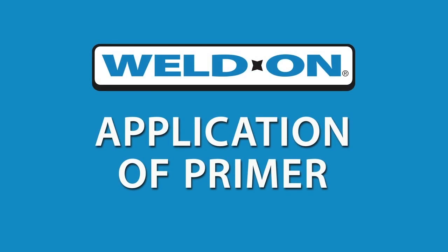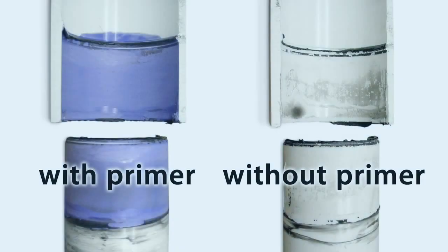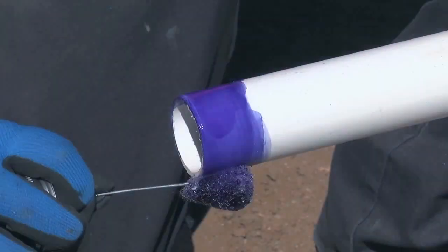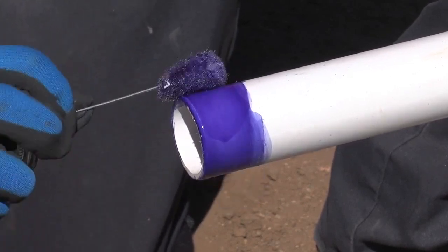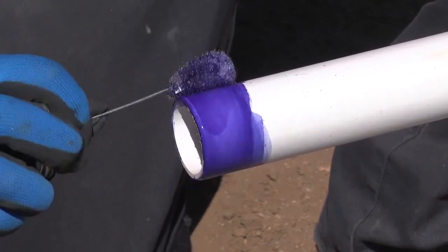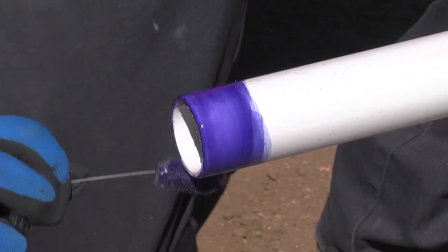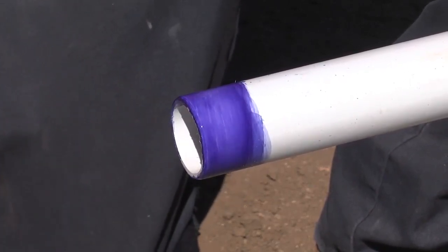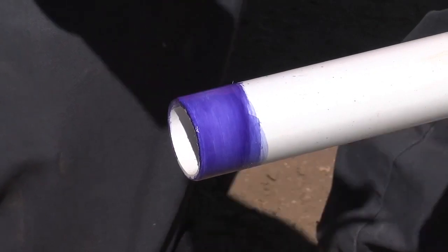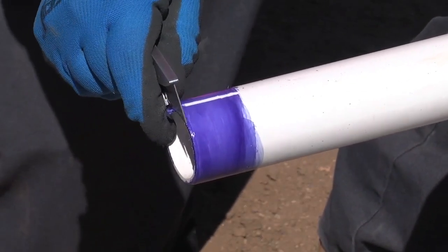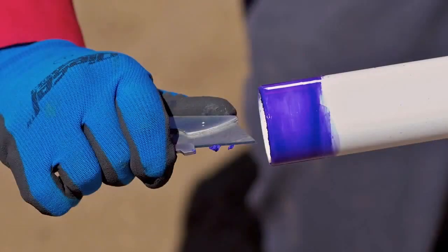The application of primer is an extremely important step in creating a first-class, long-lasting joint. Primer softens the joining surfaces and prepares them for fusion. Without primer, the surface fusion is often weak and a joint may fail. Apply primer on a scrap piece of pipe and check the penetration or softening ability of the primer by scraping a few thousandths of an inch. This will help gauge the proper amount of primer and rotational force to be applied to the joining surfaces during actual installation.